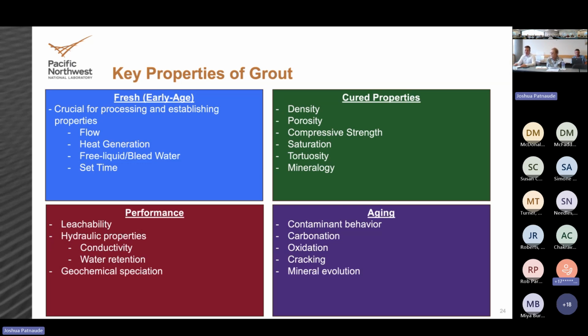Then when we take our long-term dissolution models, whether it's for a glass waste form or a grout waste form, and we apply it, we can replicate the behavior in those short-term tests, those long-term tests, those realistic tests, and those field tests, and we can take our models and replicate the behavior that a natural or ancient analog has. That gives us confidence in the ability of our model to predict long-term performance with associated uncertainty with it.